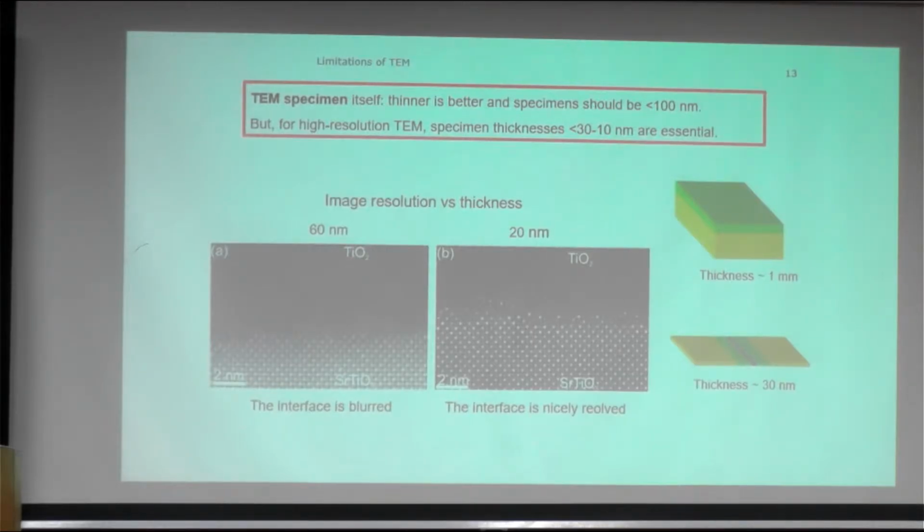Also, one limitation is the TEM specimen preparation itself, because for TEM work, we need specimens which are very thin, less than 100 nanometers. And I speak about this projection, so if your beam goes through your specimen, this specimen should be less than 100 nanometers.